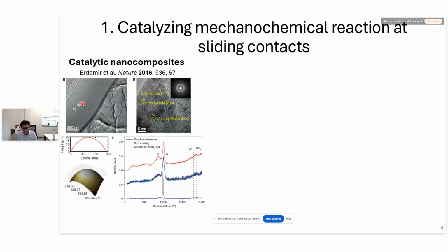tribology experiment. I should mention that they did this experiment in the presence of a hydrocarbon, so that there is an oil, a polyalphaolefin oil, at the interface, and the formation of these carbon-based tribofilms is induced by catalytic conversion of the PAO, the oil molecules, in these experiments. There have been multiple other reports on these catalytic nanocomposites, and different compositions have been tested, and I'm showing you some key references here on this slide.